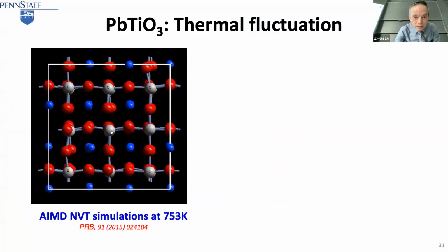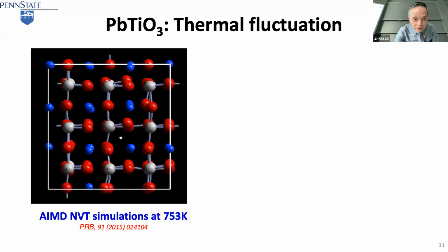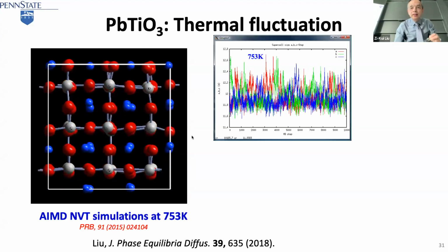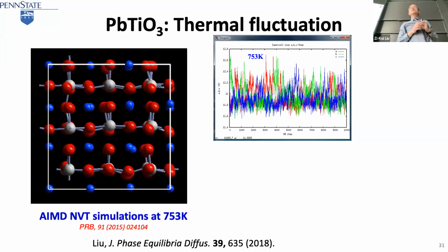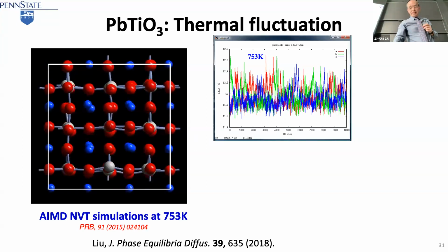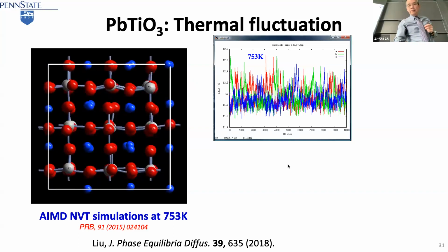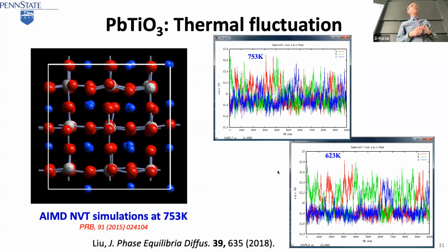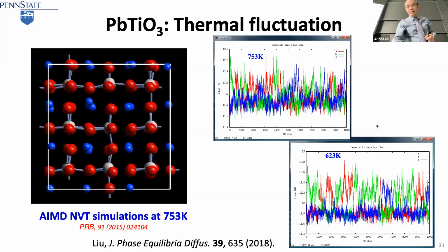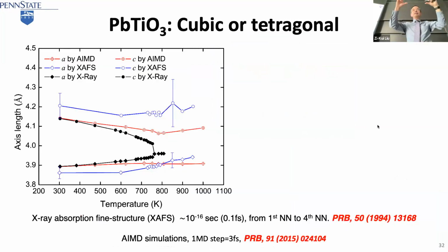but actually, of course, there are some experiments there too. This cubic, the white one, is cubic. When you look at the inside of each titanium atom, you find it's not cubic. It's always tetragonal, polarized. And if the temperature goes away from the transition temperature, it takes a longer time to change. So what it means is that if you do X-ray, you see high temperature cubic, low temperature tetragonal. However, if you do EXAFS experiments, with high resolution, you see all tetragonal.